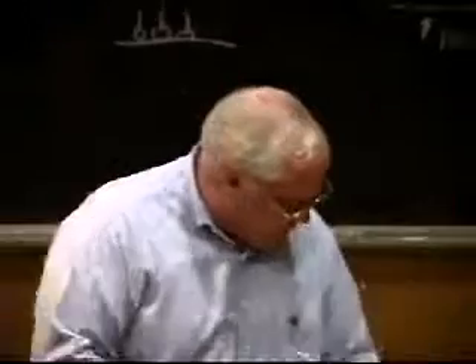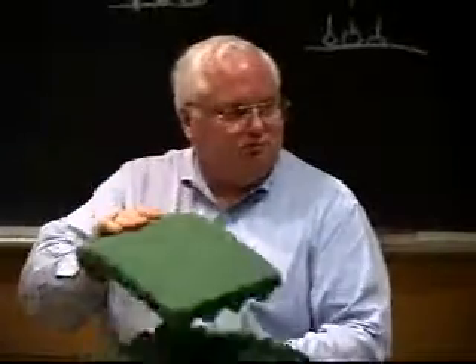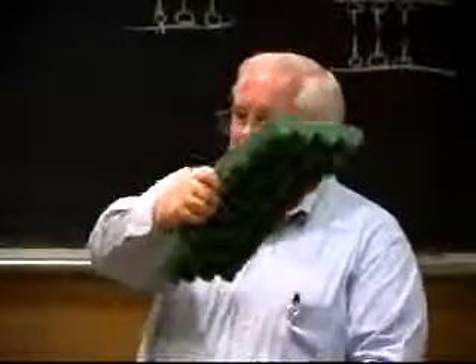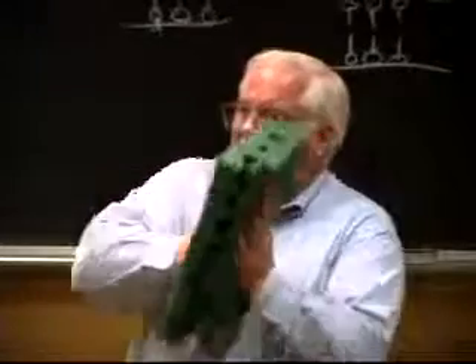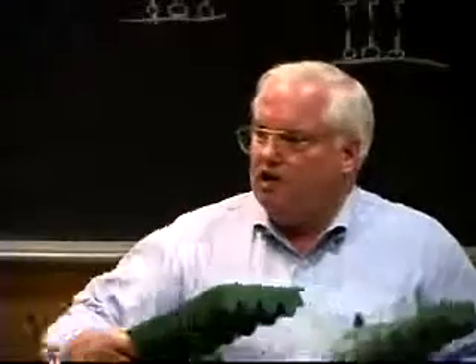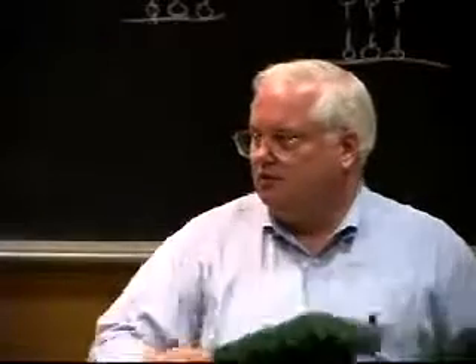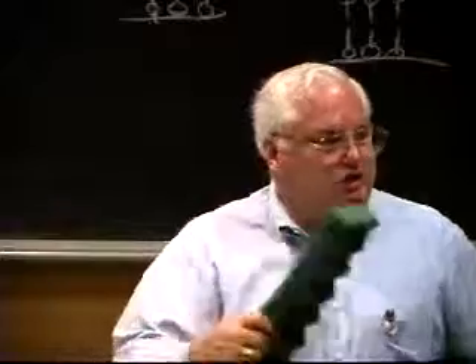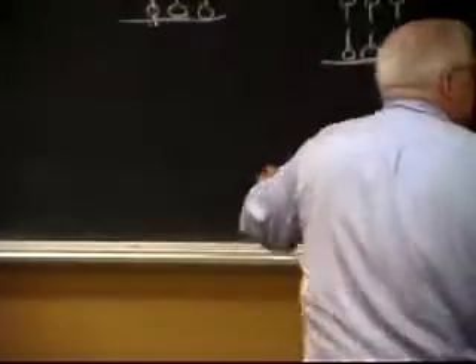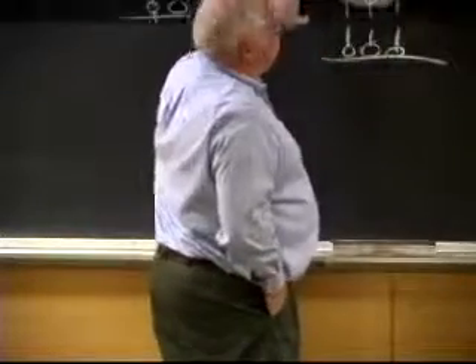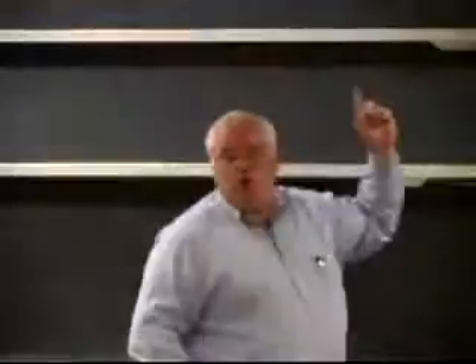Well, if I go back to this picture in here, the cross-sectional area of this thing is about 10 times the diameter of the wire. It's got about 60 to 80 microns wide as the pad that I squeeze out. And what have I done? I created a tremendous amount of shear. I just tore the mountains down by shearing them apart. I could squeeze with a straight normal force until I'm blue in the face, and I'll only get 30% area contact. If I want to use a mechanical way of getting rid of the surface roughness, I need shear to break things down. And I need to do something to get rid of the contamination. The way I get rid of the contamination in thermocompression bonding for semiconductors is to use gold and a little bit of temperature. Gold and a little bit of temperature just drive off the stuff.